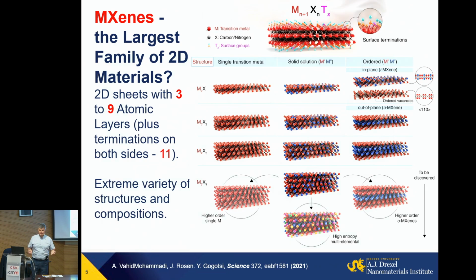So what do we have today? We have actually a very large family of materials, of which only about 50 basic structures, not counting surface terminations, have been reported. A couple of dozen solid solutions, as I mentioned, where we can mix and match the M element and actually make high entropy multi-elemental MXenes with up to 7 different transition metals. But we can also make even more complex structures, atomic sandwiches out of an in-plane ordered MXene, where one element, for example, chromium, is on the surface, and another element, for example, titanium, is in the middle. The outer element will determine electrochemical, chemical, catalytic properties of the system. The inner layer will determine transport properties, electron transport, for example, here.